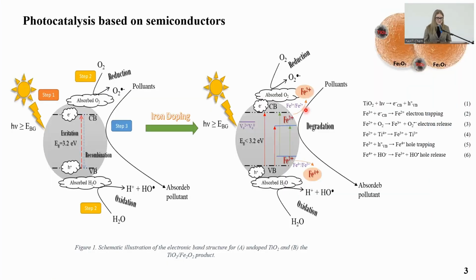Starting with the principles of photocatalysis, Figure 1 shows a schematic illustration of the electron-hole pair generation for undoped titanium dioxide and titanium dioxide doped with the iron product. In this study, we use titanium dioxide as a photocatalyst due to its high level of activity in many photocatalytic reaction systems. Doping with iron could induce many more oxygen vacancies, which favor the absorption of water and formation of hydroxyl radicals. Iron oxide can also act as recombination centers for the electron-hole pairs when their concentration is high, according to the reactions on this slide.